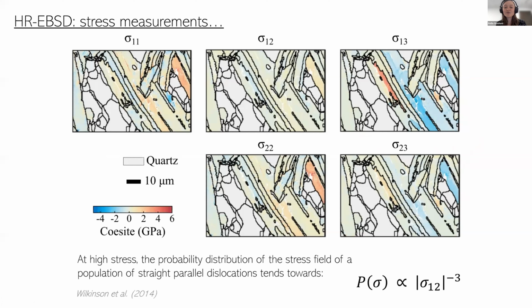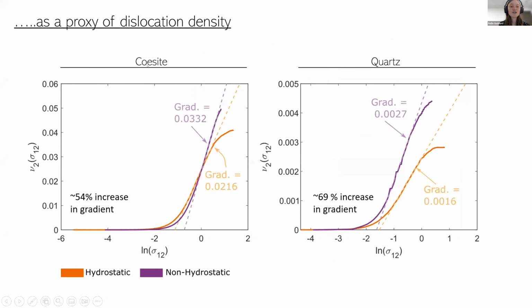And the cool thing is that we can look at the shape of the probability distribution of this stress field to give an idea of whether it is controlled by dislocations, because if it is, it will follow this theoretical relationship. And to analyze the shape of the probability distribution, we do something called the restricted second moment, which is what I've done here for sigma one two. And I've put it up here for coesite and quartz. So you've got the restricted second moment on the y-axis and the stress on the x-axis. And we've done it both for the hydrostatic sample and the non-hydrostatic sample.